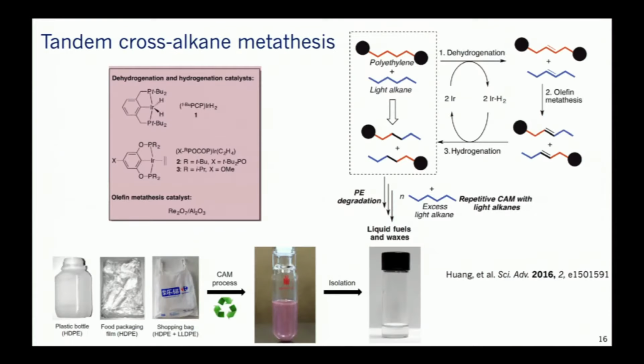Another approach to taking commodity polymers apart involves the use of catalysts to cleave what are much less reactive carbon-carbon bonds. And in this case, the strategy is to install a linkage which is more reactive, an olefin linkage, in these carbon-carbon single bond backbone polymers. So the alkane metathesis process is a process that involves forming olefins which are susceptible to olefin metathesis. The first catalyst here is part of a dual process involving an iridium catalyst, which takes the polyethylene backbone and installs the double bonds, and at the same time does that with light alkanes, which are added as a solvent for the process.